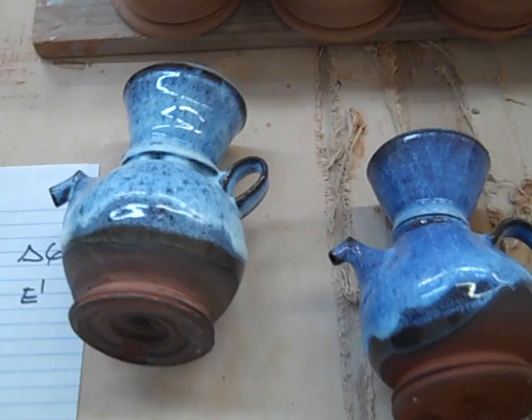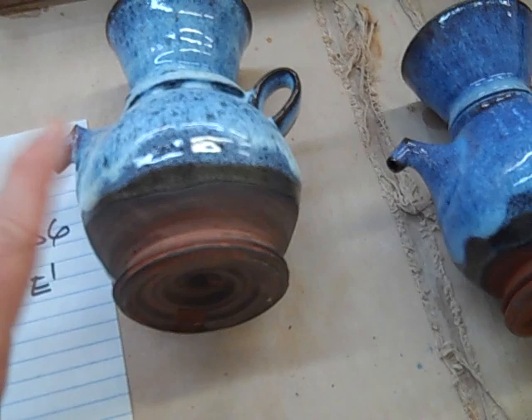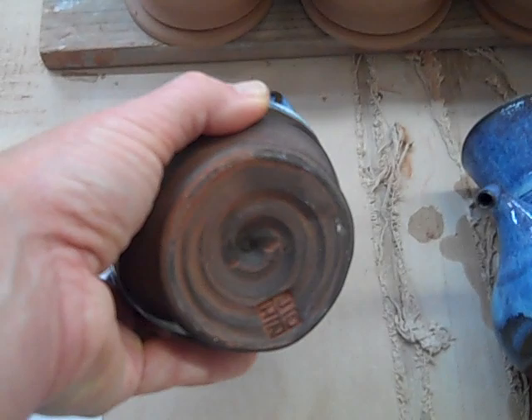Basically I ball mill laterite for two hours. You can decant it if you want. But I dip it in real quick and it'll get this kind of splotchy color. If I dip it in a little longer, it'll be darker. See how it's like a little uneven — I kind of like it when it's uneven. It makes it look more reduction-fired.